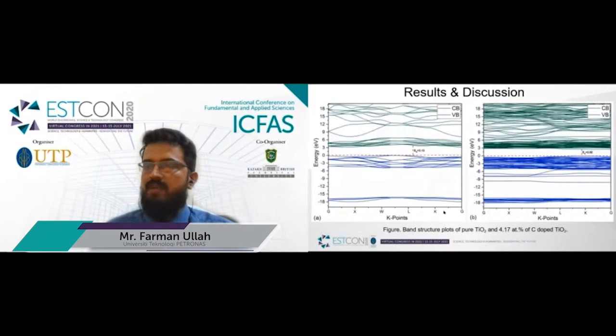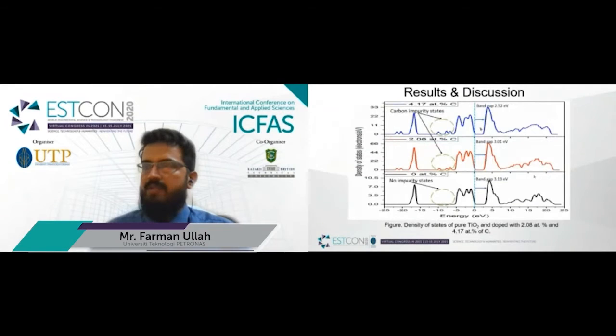Band structure plots for pure TiO2 and carbon doped TiO2 are also shown here. Figure A represents the band structure plot for TiO2. The blue states represent valence bands, and the green represents the conduction band. The red dashed line represents the Fermi energy level. The band gap energy is 3.13 eV for pure TiO2, and for the carbon doped TiO2 model it is reduced to 2.52 electron volt.